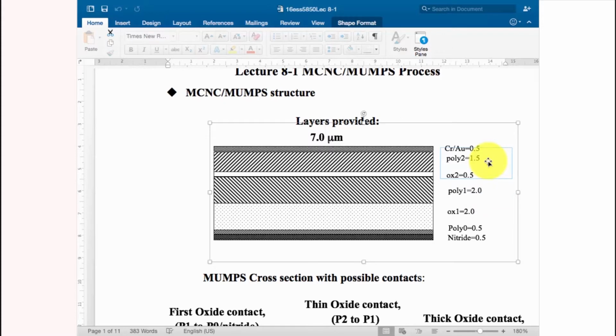But when you compare these two polysilicon layers to the original CMOS process, the polysilicon layer is much thicker, right? The original polysilicon structure is only 1 micron at most, 0.8 micron. So here, if you combine these two structures together, you can easily get 3.5 micron. So it's much thicker than before. And also two sacrificial layers. One is oxide one, which is also very thick, 2 micron. So in the past, we didn't apply the sacrificial layer so thick.